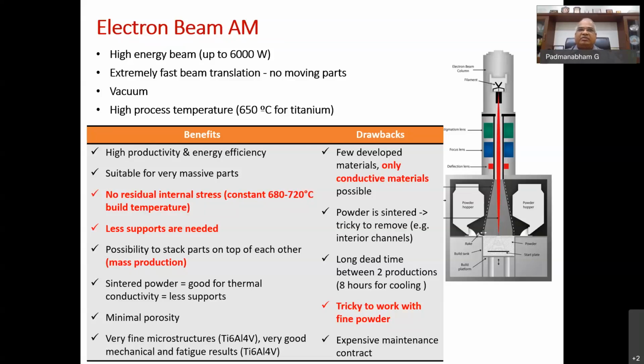Then the processing is done in vacuum, because unless it is vacuum, your electron beams get scattered or diverged. So you have to do the processing in vacuum. And then the bed that you are melting using the electron beam also is at higher temperature. Basically, for a better coupling of the beam, the electron beam is first scanned on the bed to form a cake first, and then the melting scan happens, because of which the bed is maintained at 650 degrees centigrade, and then once you have a higher bed temperature, the thermal gradients that the melting and solidification layer will experience will be less, and because of which you have less residual stresses.